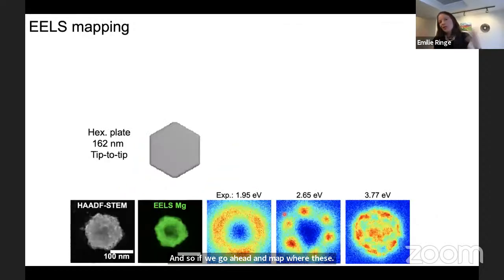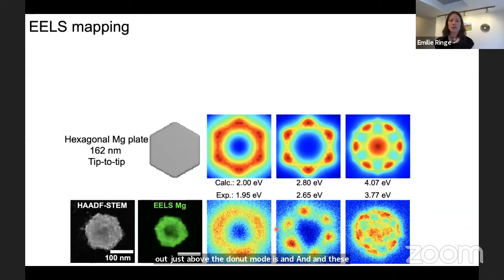So if we go ahead and map where these modes appear around our particle, we get what people might call plasmon maps - loss probability distributions at different energies. For instance, here you get a mode that is kind of symmetrical, looks like a donut. Then you have a mode that has high probability of loss around the tips, and then something that has high probability of loss around the edge and the center. If you're an experimentalist like me, you'll spend the rest of your life calling this the donut mode, or you call up amazing theorists who can help you figure out just what the donut mode is. These theorists are here in Cambridge, and it's just been wonderful.